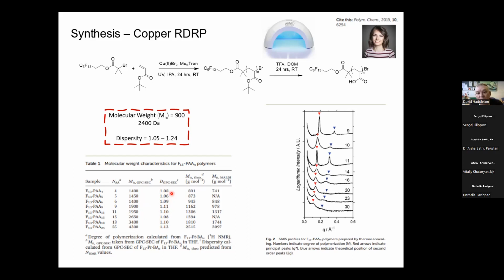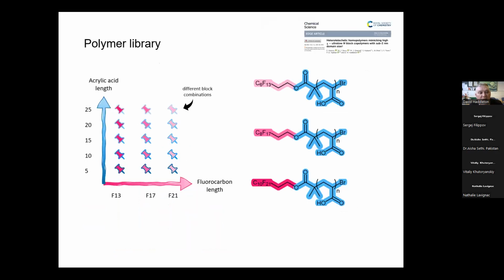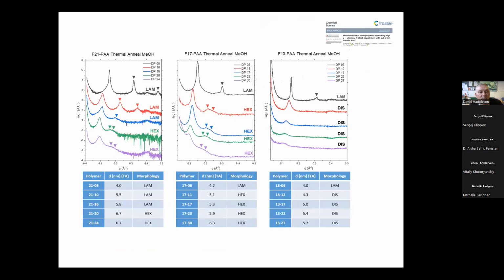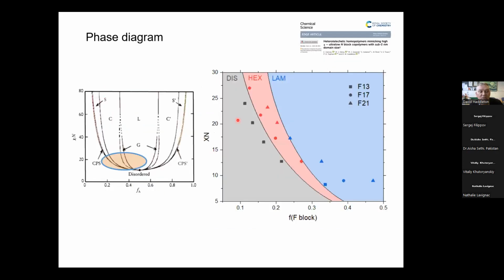Then we would cause them to do phase separation, and we do SAXS, and then we can change the length of the fluorinated group. This is C6, C8, C10, so we've got 13, 17 or 21 fluorines. We can change N by going 5, 10, 15, 20, 25, and then we cast them as films, we anneal them, and they will self-assemble. Some of them won't, they go disordered, some of them will be lamellar, and some of them will be hexagonal. And we can then map that space, and by mapping that space, we can then get the phase diagram. So here we've got disordered, then we can move into hexagonal, and then we can move into lamellar.